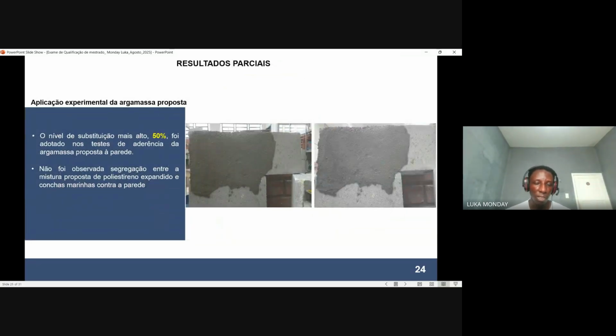Based on this, an experimental application of this material was done to show whether it can be applied as an insulation mortar without any segregation from the actual mortar, using the highest substitution level of 50% for both materials. It clearly shows that this material adheres to the wall without any segregation between the wall and the material, as seen here. However, some little dots, some traces of EPS, were still noticed.